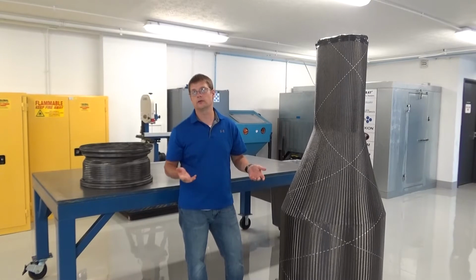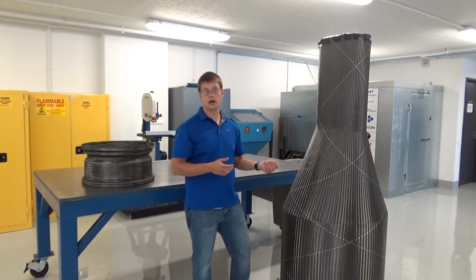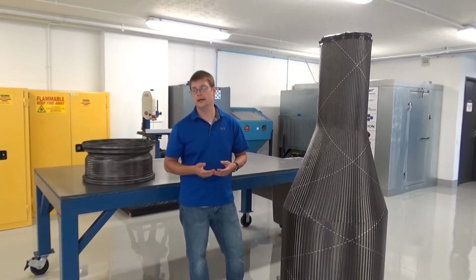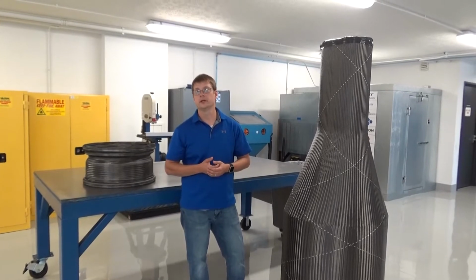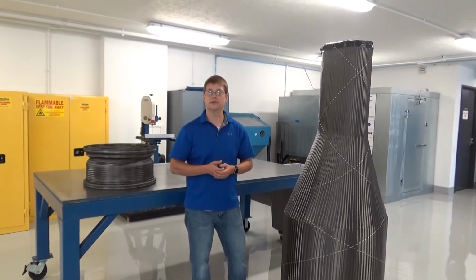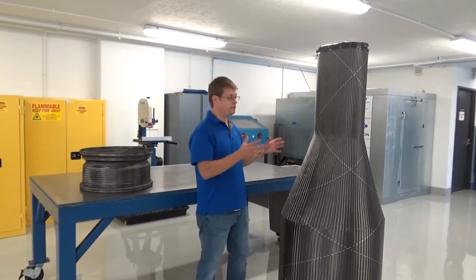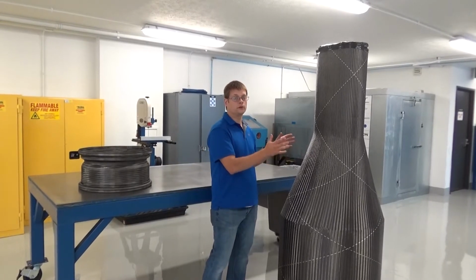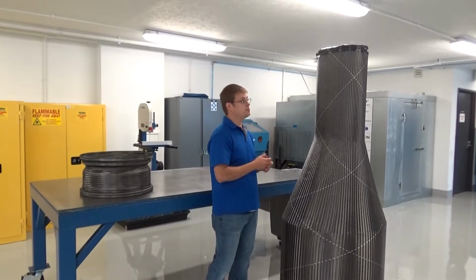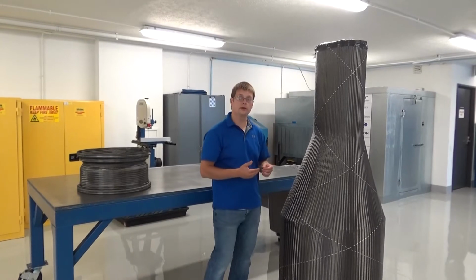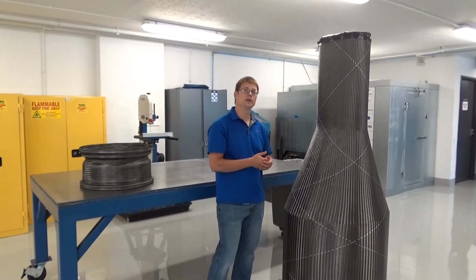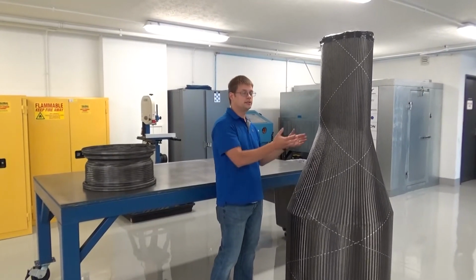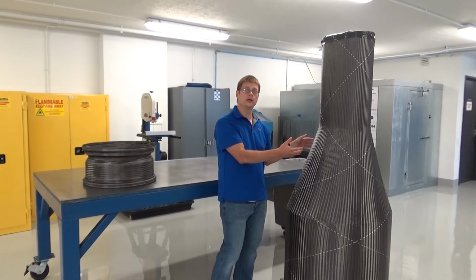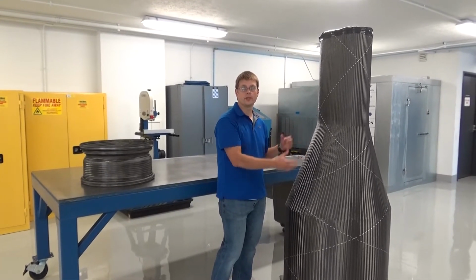So our largest cell can handle mandrels weighing up to 2 tons. They can be 12 feet long and up to 10 foot in diameter. So if you couple that with our 864 carrier, we can produce very large scale overbraided preforms. It's also pretty neat because we can do multiple layers and we can add tackification. So what our customer would get is essentially a semi-rigidized preform that they can drop into their tooling.